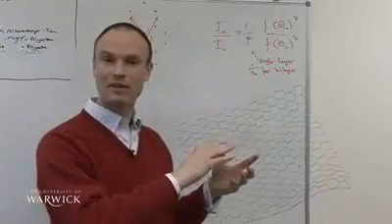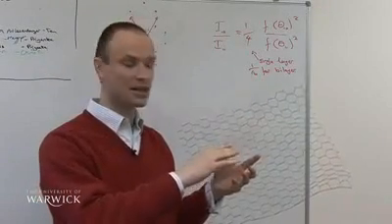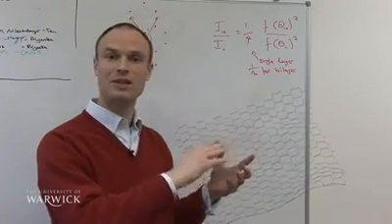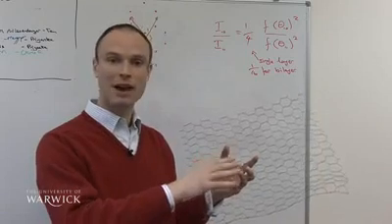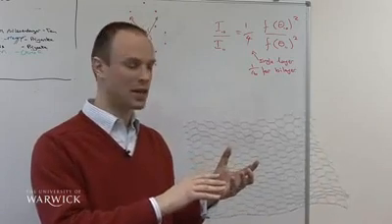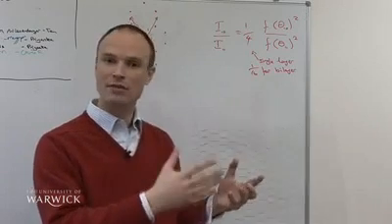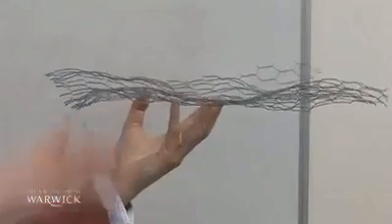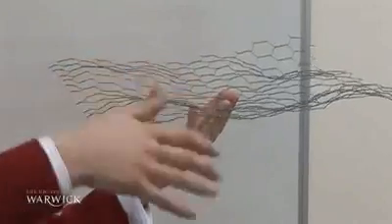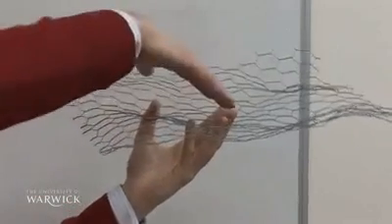The wavelength of these ripples in graphene is a few nanometres to 25 nanometres, and their amplitude is about 1 nanometre. They're really surprising because they have high strain energy and they impact on the charge transport properties.